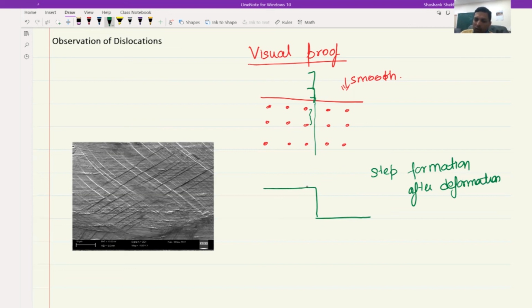So this step is not formed by just one layer of atoms. If you are able to observe it, it is most likely formed by tens of thousands of such dislocations accumulating and making this very large step. And therefore this is a slip line, where dislocations have moved and formed these steps. I have not drawn it to the same scale, as you can see, because I wanted to emphasize the fact that the steps are not just one layer of atoms, but several layers of atoms.